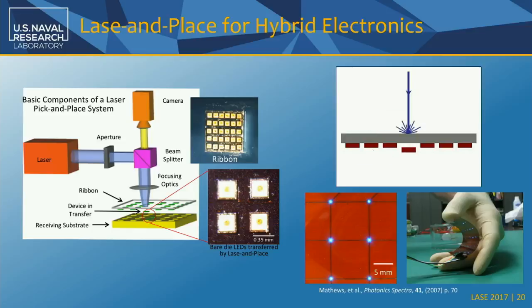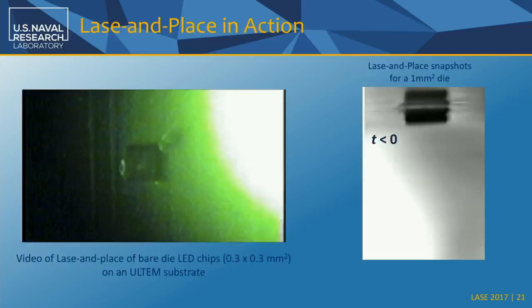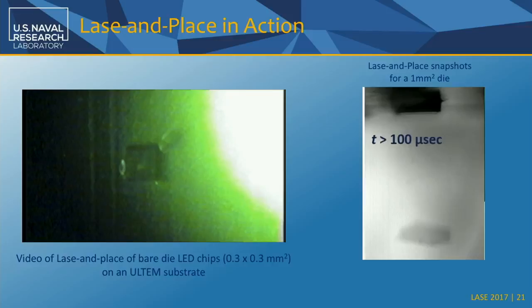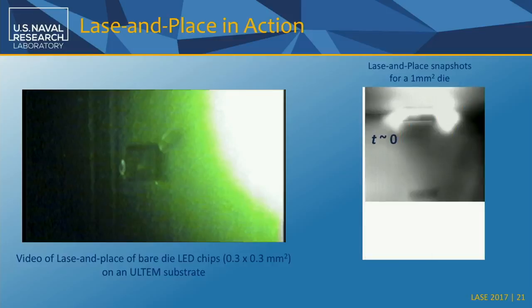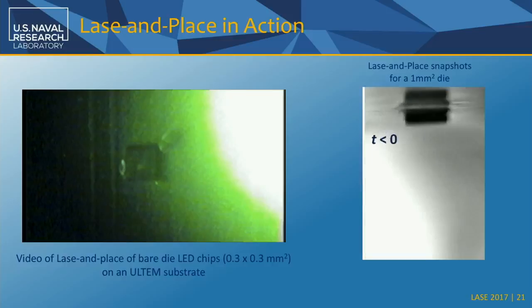In other techniques that use long wave lasers to do transfer, using effectively a thermal process rather than an ablative process, they have to put the devices upside down because they have excessive heat that can damage your semiconductor patterns. The disadvantage of that is that your device is facing down and you don't know where the interconnects are, you don't know where the pads are, so it makes it more difficult to make a circuit. By transferring the devices face up, it's relatively easy for us to come in and connect them and make a circuit that way. So with Lase-and-Place, we have been able to make arrays of devices, with the goal of moving towards this hybrid approach.